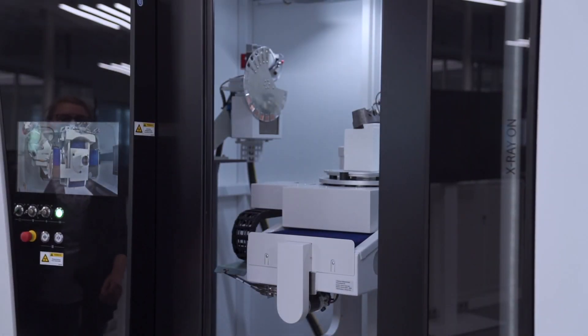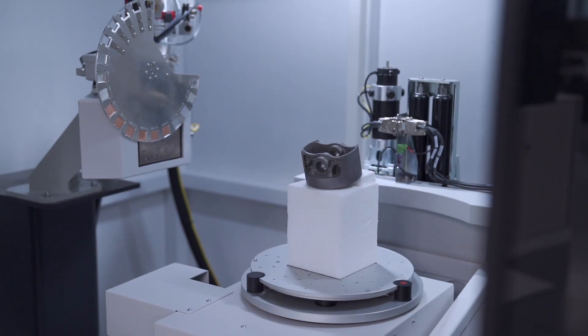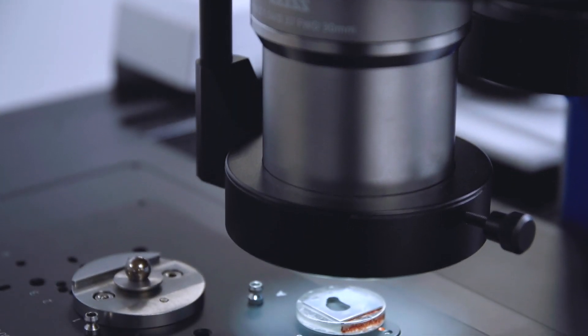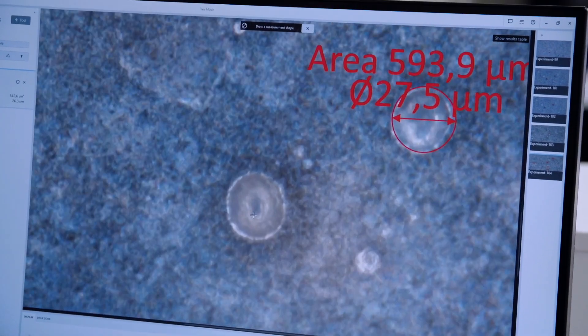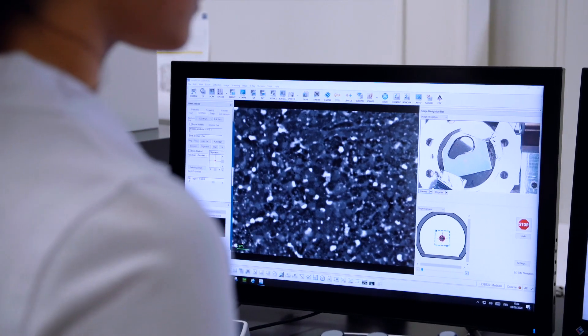The next quality inspection step uses a high-resolution X-ray CT to detect any cavities or material impurities in the structure. This material inspection after printing is particularly important for the highly strained pistons. Even once we control the additive manufacturing process to minimize distortions and defect density, we still need a proper microstructure to have adequate mechanical properties. Grain structuring and phase assessment before and after post-processing is used to define specific heat treatments for additive manufacturing.